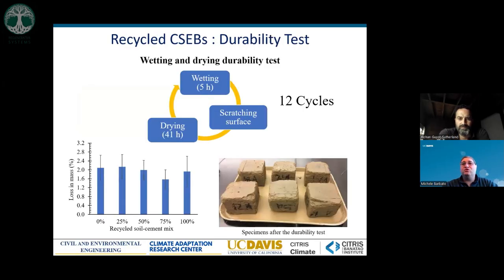We did also our durability test. And here we were pleasantly surprised to find out that fundamentally usage of recycled soil has no statistically significant effect on the durability. We have a loss in mass that is overall smaller than 2% at all of the different levels of recycled soil. Fundamentally, the outcome of this research is that for construction purposes, you can reuse 100% of the material. It's 100% recyclable, which is a nice thing to have.